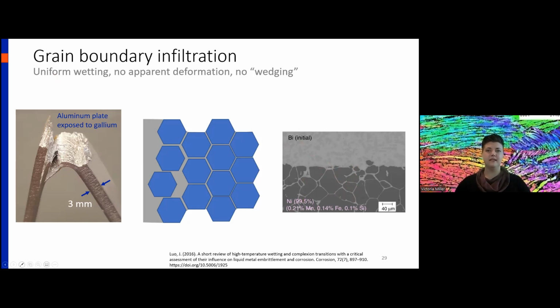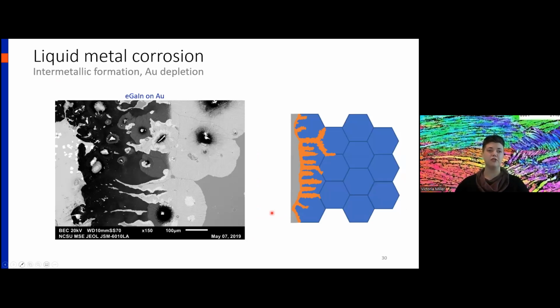And then the final mechanism is liquid metal corrosion. So this is eutectic gallium indium liquid on gold. And as you can see, there's a lot of stuff going on. There's formation of various intermetallics. There is local oxidation. There is this puddle of liquid that has small crystals growing within it. There's a lot happening. You can also get a much simpler morphology.